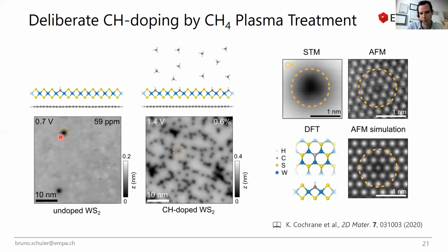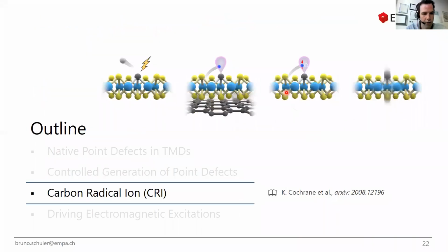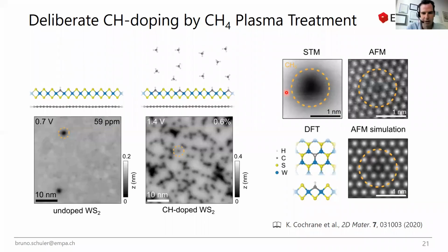And in this case, we actually used this to assign what this dark defect was, because this was a kind of tricky one to assign. But now knowing that they did this methane plasma treatment and that we see this defect all over the place, we could assign it to this carbon hydrogen complex, and also the AFM makes sense if you simulate it with the code developed by Pavel. And now we will stick to this defect for a while.